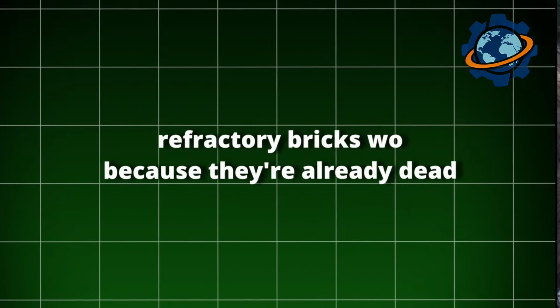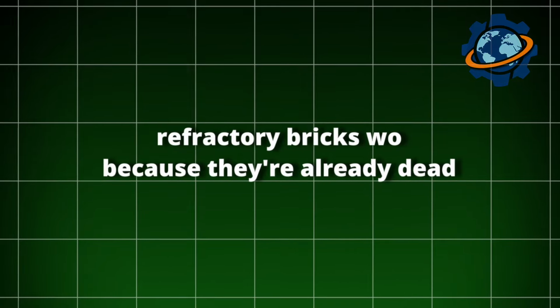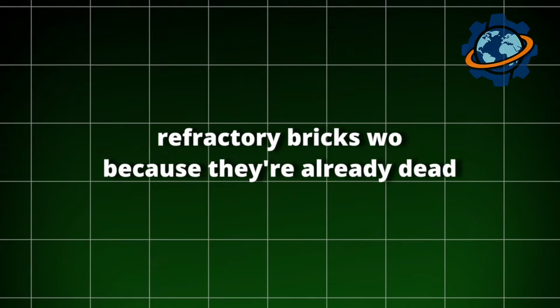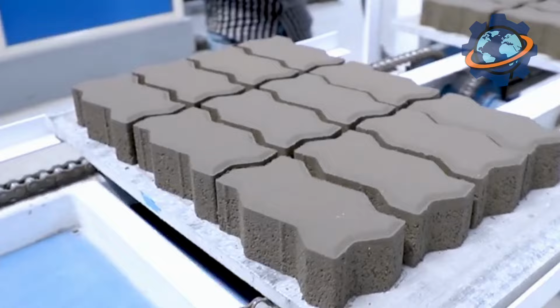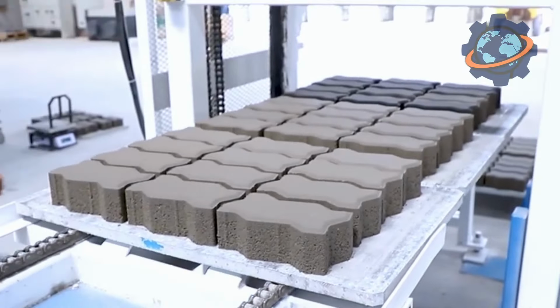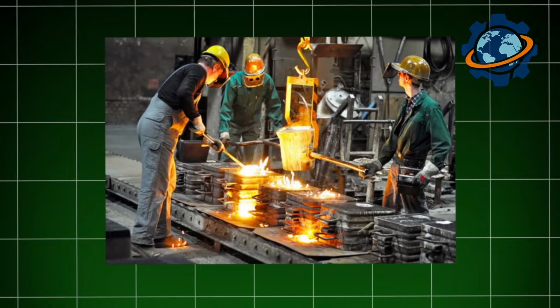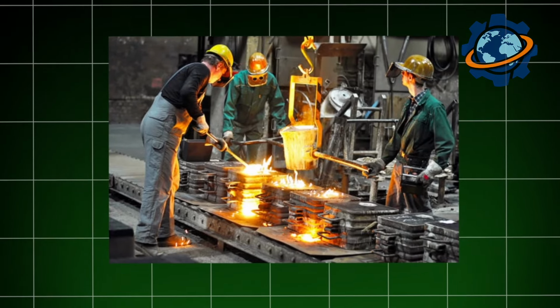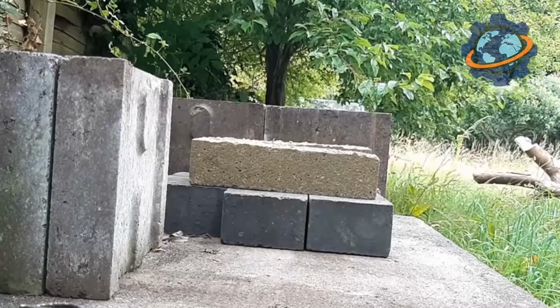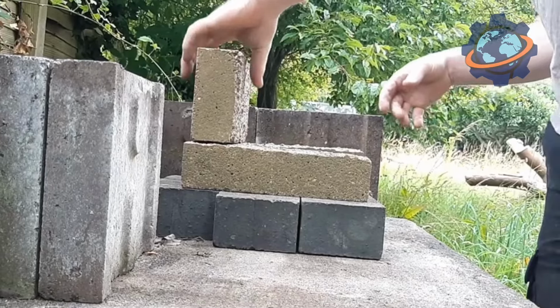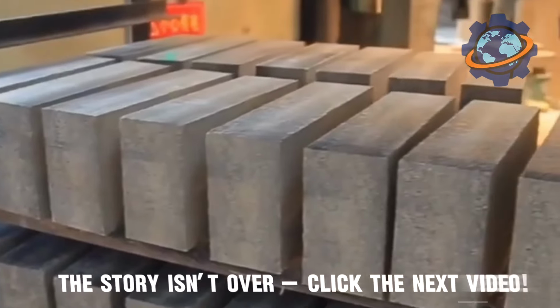Here's the secret we promised. Refractory bricks work because they're already dead. That double firing process, burning the clay into chamotte, then mixing it with fresh clay and firing again, creates material that's experienced worse than anything it'll face. The chamotte has no shrinkage left to give. The fresh clay binds it together, then dies itself during final firing, becoming equally stable.